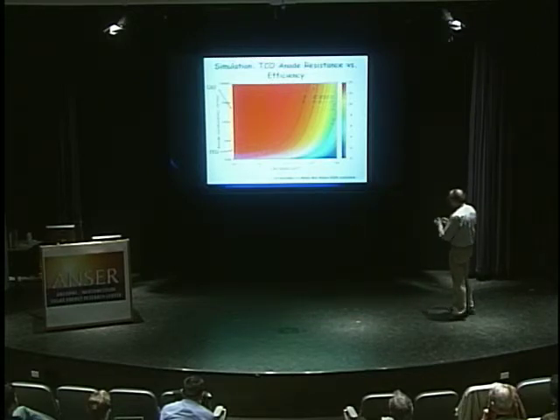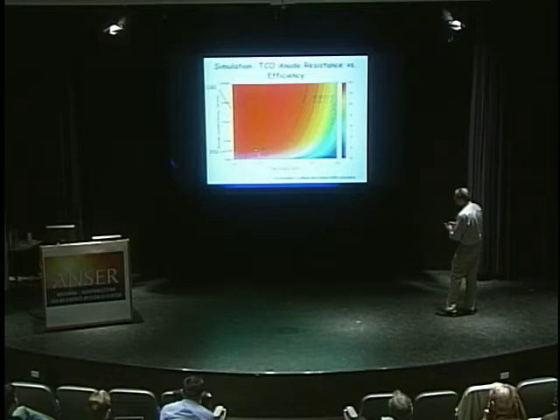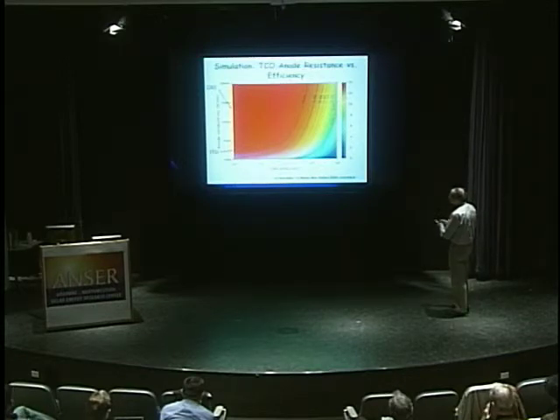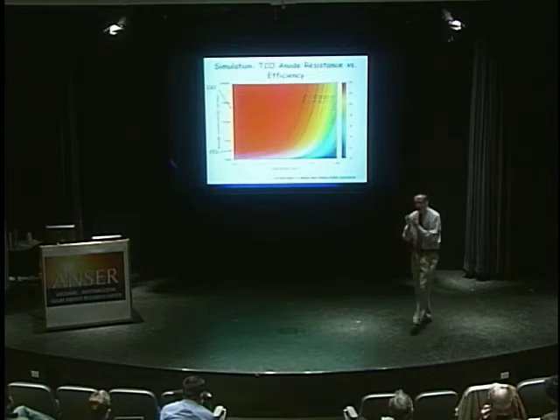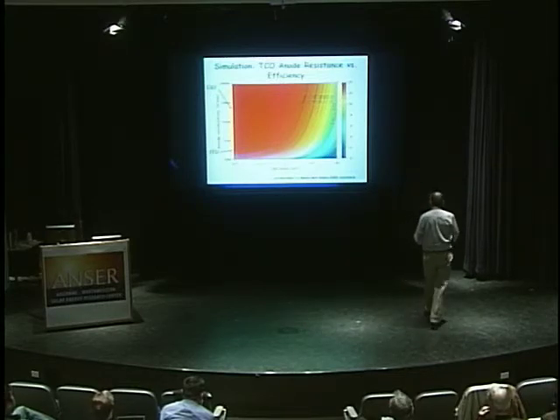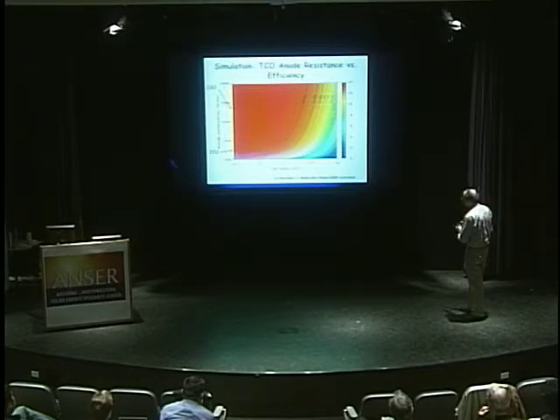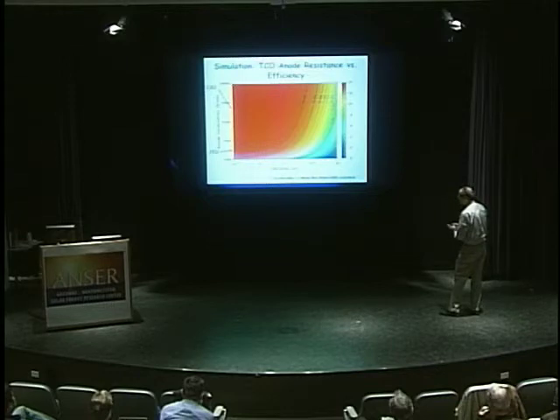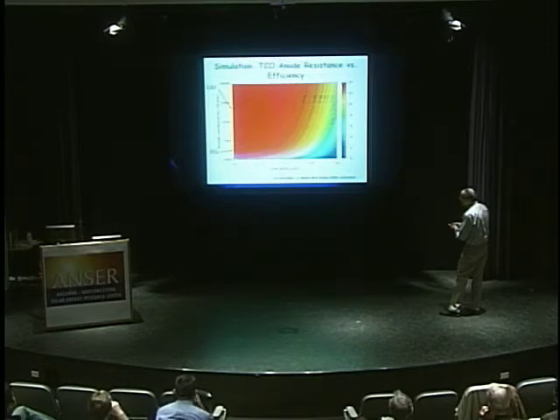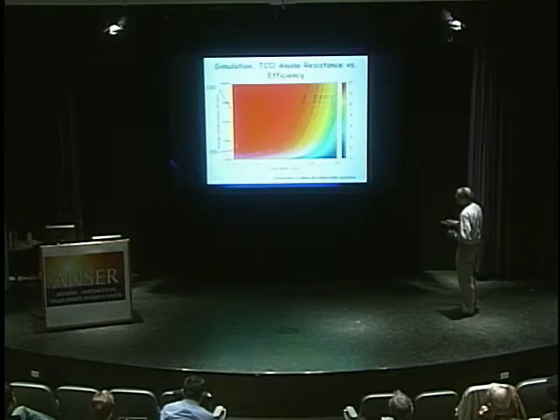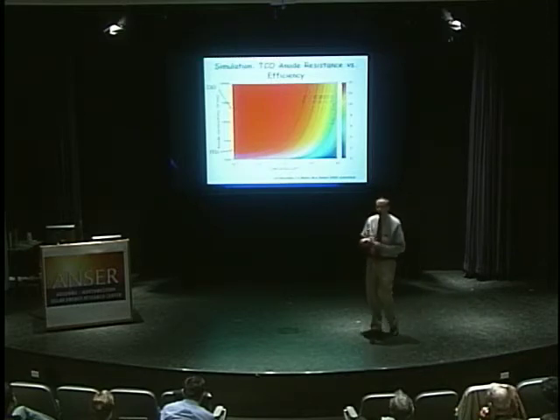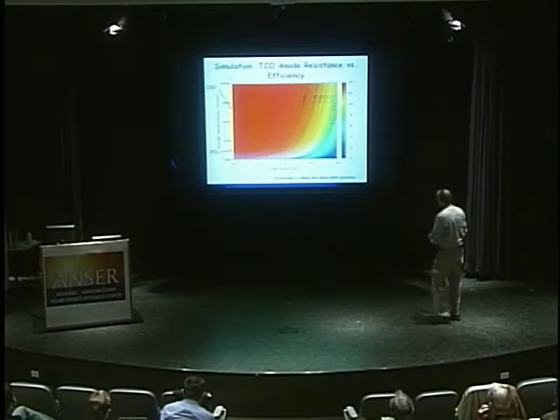If I have a cell with 12% efficiency using ITO for a very small cell, to make it a large cell I've got to dramatically increase the conductivity of the transparent conducting anode, or I'm in big trouble. So I can gain a lot, and these are different families of curves. If I have a 12% cell, I can get good efficiencies with a poorly conductive TCO. But as I start making the cell larger and larger, I can't hold that 12.5% unless I go to higher and higher conductivities.